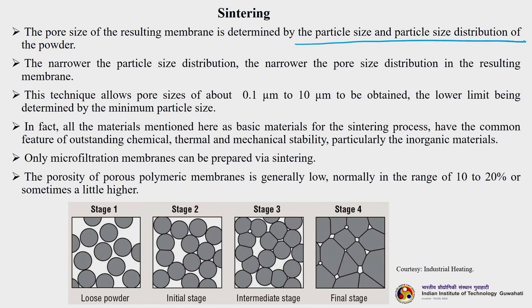Powder means your material from which you are going to make your membrane. So, the narrower the particle size distribution, the narrower the pore size distribution in the resulting membrane. So, if we get a very narrow particle size distribution something like this, then we will also get a very narrow membrane pore size distribution. So, this technique allows a pore size of about 0.1 micron to 10 micron, okay.